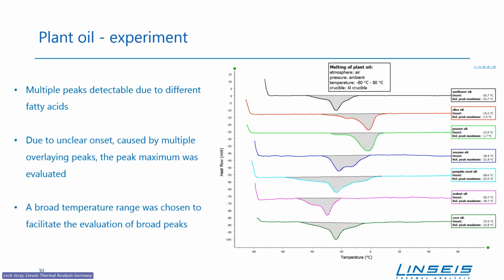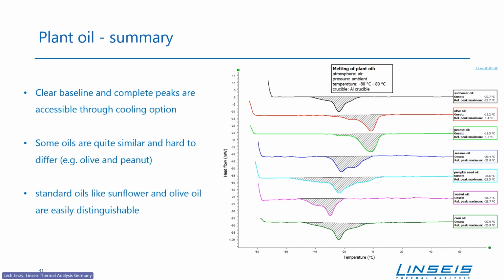So different oils, as expected, have different curve shapes and melting points. We have here sunflower oil, olive oil, peanut oil, sesame oil, pumpkin seed oil, walnut oil, and corn oil. Peaks are within the region of melting of each mixture of fats, of oil fats. We use the instrument with cooling option. The application for the end user is product falsification and potential quality issues. We have a clear baseline, and we see the peaks which come from the melting process. If we raise the temperature, we see the endothermal peaks.